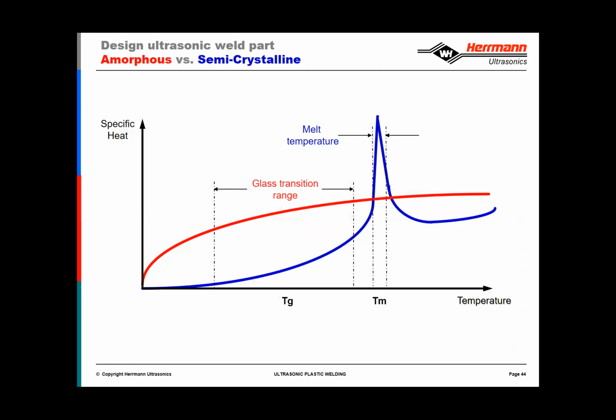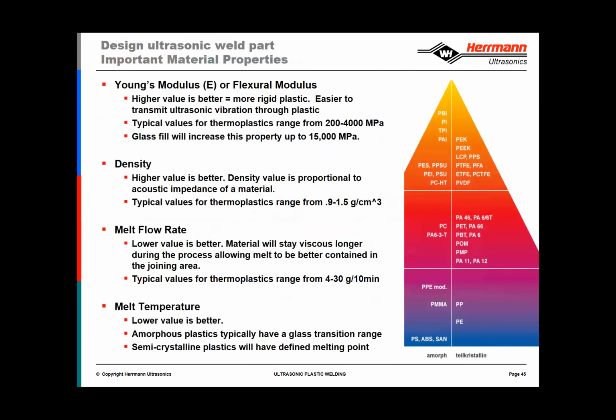So when we think about the energy director, or the area that is intended to melt and cause the bond in a semi-crystalline material, because it becomes liquid very quickly, the joining velocity can also change, and therefore that molten material, instead of being contained within the area to be welded, can very quickly spread and move out of the joint area, and therefore create a weak bond. So for that reason, primarily, semi-crystalline materials are more difficult for bonding. It's not to say that they can't be bonded, but again, we just have to take special precautions and different parameters than we would normally use to get them to bond.